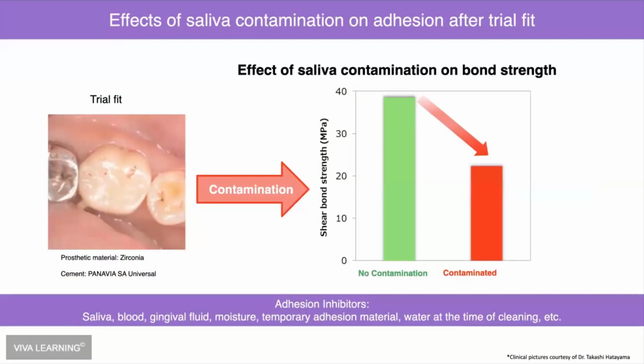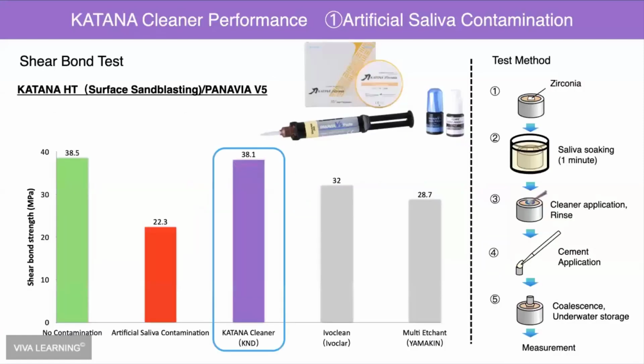And we can see that when we get saliva in the way of things, which is why when we bond we need to have the tooth as clean as possible, the bond strengths get lower. You can see when we put Katana cleaner back onto our crowns and clean it up, we get that crown just as strong as it was before we actually tried it in. When we're trying it in and not cleaning it out, or just cleaning it out with water and air, we're actually losing almost half of that strength. So add that cleaner into your system.